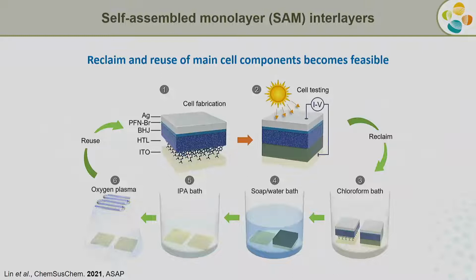What we also identify is that once we use these single molecule layers, you can actually start thinking of recycling and reclaiming and reusing part of that cell, because these monolayers are actually very gentle. They functionalize covalently very strongly on the surface of this electrode, but they don't damage it like other technologies do. As a result, you can potentially take the substrate, remove all the metals and reuse them if you want, but also take the substrate, which is the largest part of the volume of the material we're using. The plastic substrate or paper or glass we're using to build these devices on are essentially millimeter thick when compared to a few hundreds of nanometer of the active layer.